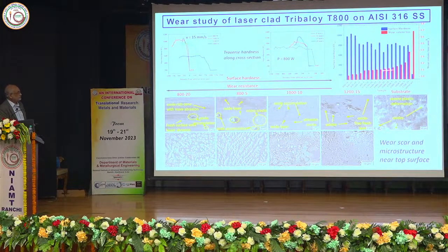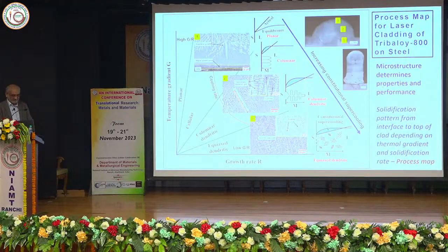What he is trying to show is that if I grade the composition appropriately, I can change the hardness and the wear resistance accordingly. To do that, you develop various types of microstructure. You can clearly see that the nature of the microstructure and its constituents are different, and one can do a complete mapping.